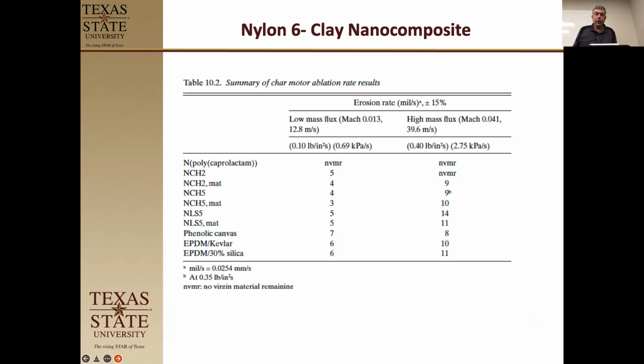Okay. So in this result here, they wanted to do a kind of comparison. The speed of the gas running through there is Mach 0.013. And then they had a low mass flux, which is this 12. So what they're saying is that they're blowing hot gases with aluminum particles in them across there, and we're looking for how much it ablated. Here, this is your erosion rate in mils per second. Notice these right here: no virgin material remains. That means it burned through. That's bad. That's a fail.